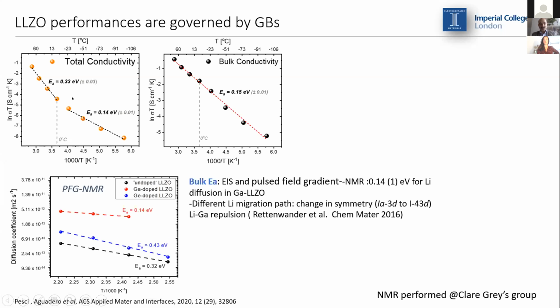In order to understand what was going on, we deconvoluted, as I said, bulk and grain boundaries contribution. If we look at the contribution of the bulk on the total conductivity Arrhenius plot, we see actually that the bulk doesn't undergo any change in activation energy in all the temperature range. It's got a very, very low value of activation energy. In fact, it's one of the lowest reported in the literature.